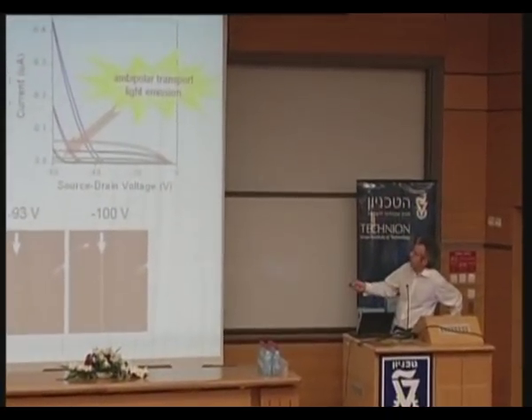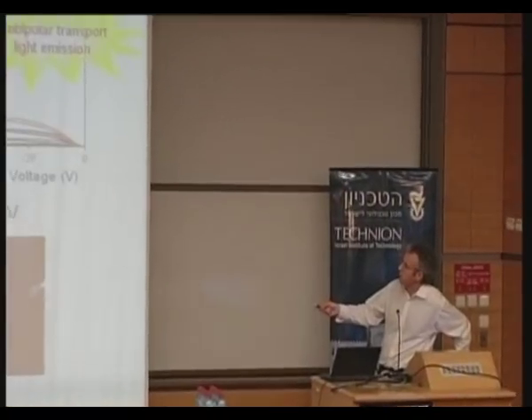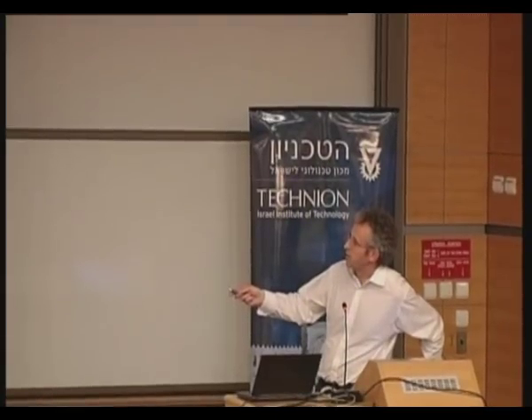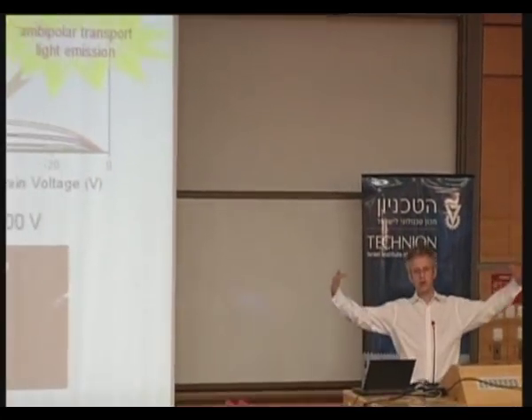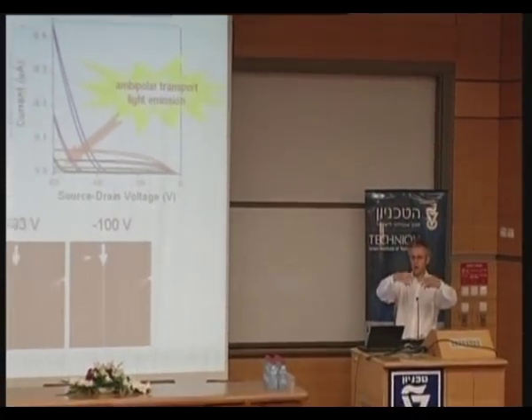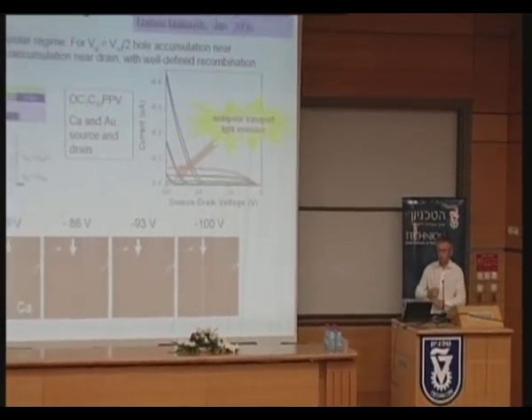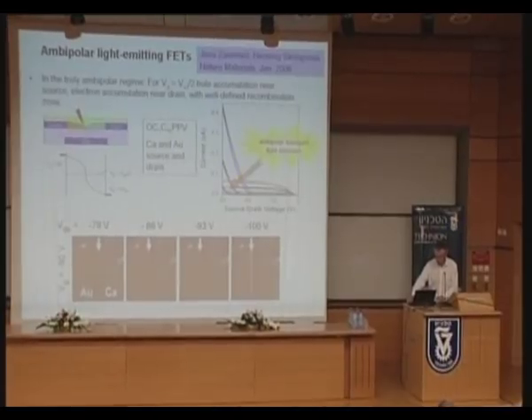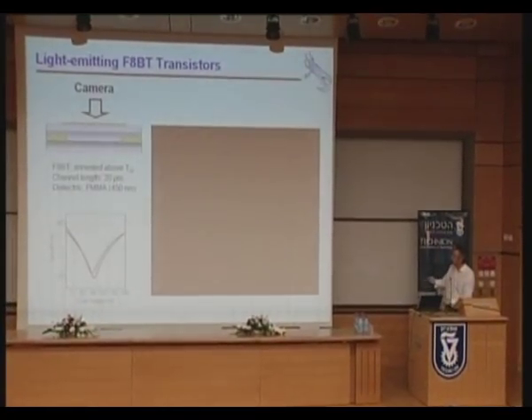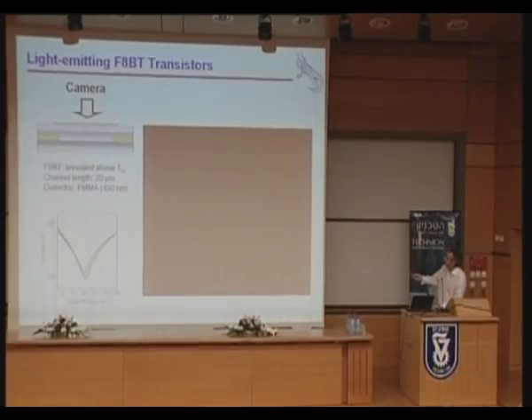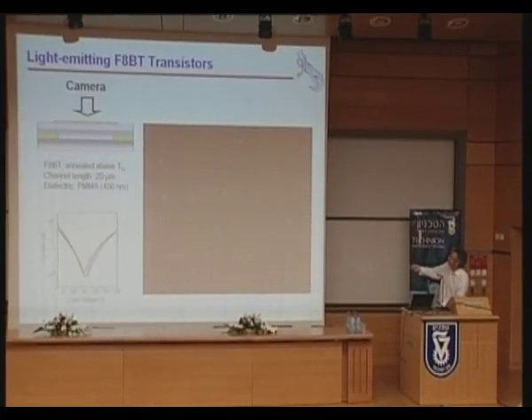And the idea is that if we hold the gate voltage midway, say, between the source and the drain voltage, to one side we're going to induce positive charges at the dielectric semiconductor interface, and to the other side, negative charges. And they're both drifting towards one another, and where electron meets hole, well, we should get formation of an exciton and light emission. And I'll take you through to the one that works best, and I'm afraid, I don't know whether it's possible to turn any lights down, but what we have here are 20 micron separation between source and drain interdigitated electrodes.